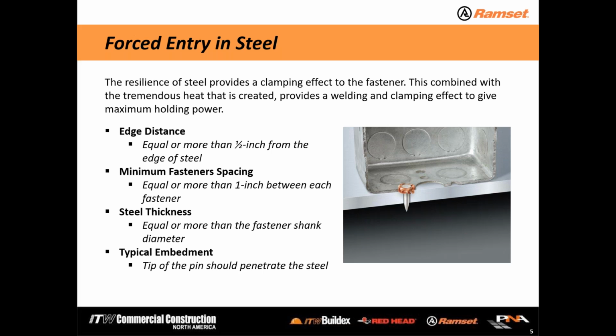So edge distance and spacing are a little different than concrete here. This is something that we want to take a look at. You want to stay about 1/2 inch away from the edge, and the edge is any physical edge, to the center line of the pin. And the 1/2 inch edge, really, if you think about a powder actuated tool or a gas tool, that's about the diameter of the fastener guide or the muzzle that the pin exits from. So we want to be sure that that edge of the tool is completely on the work surface so as not to cause the pin to exit in free flight or something like that.